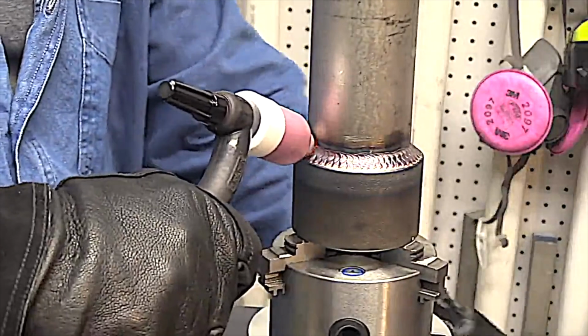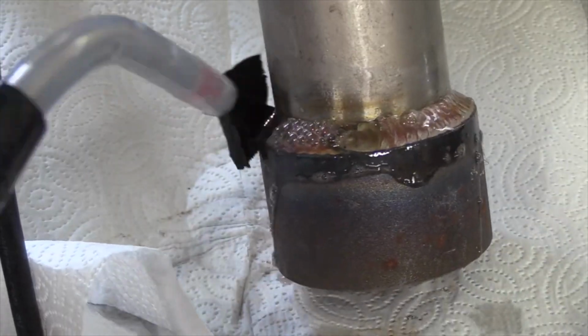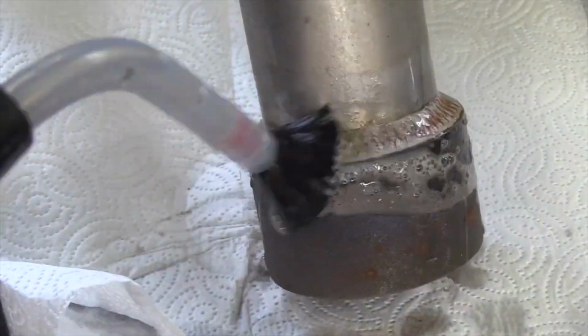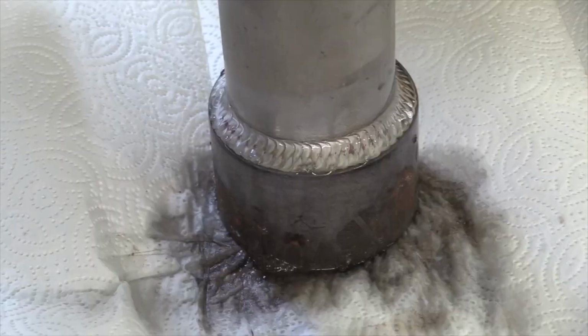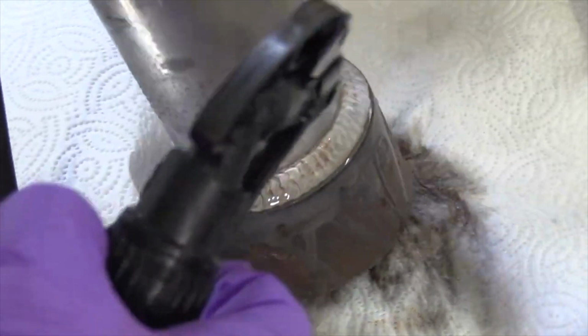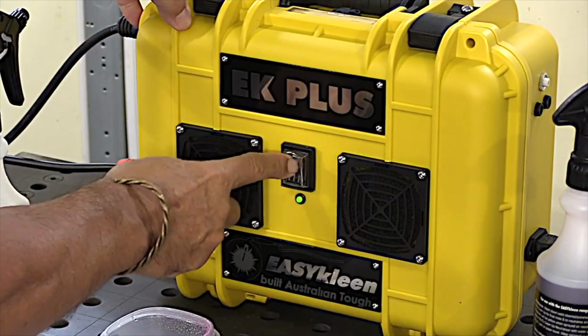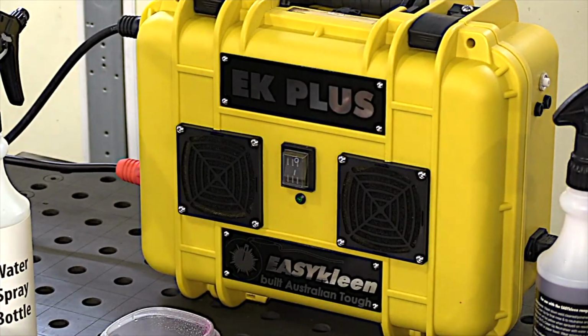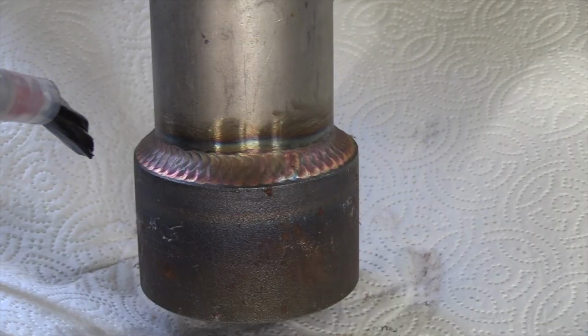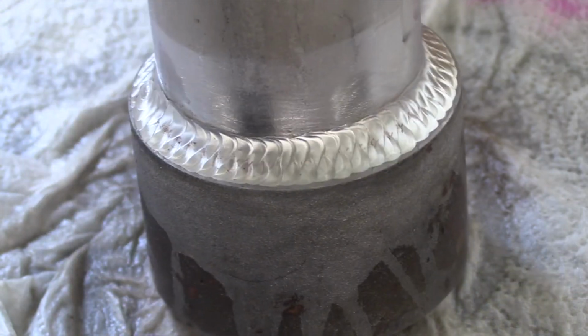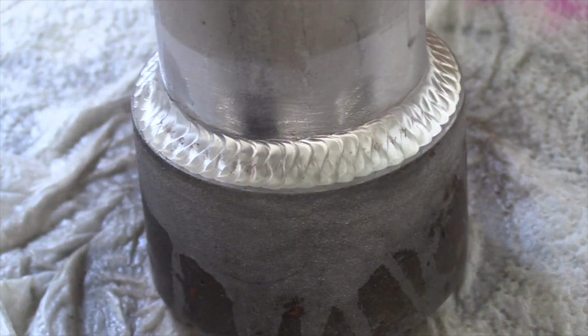Discoloration on stainless steel is something that usually you just wire brush off and that's good enough. But there are certain industries and certain applications where that's not good enough, and you need more corrosion resistance than that offers. And when that's the case, electropolishing and passivation is needed to restore corrosion resistance to the surface of a welded joint. I got my hands on an EasyKleen electropolishing unit and did a video on how easy it is to remove discoloration from several different types of stainless welds.